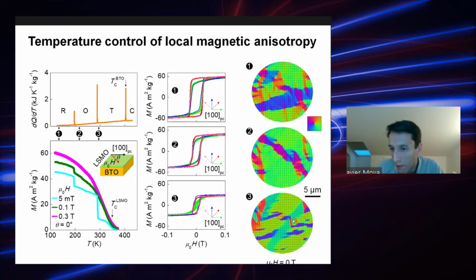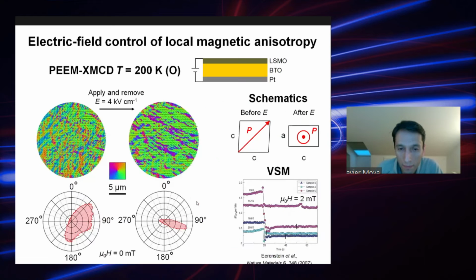We've done magnetic imaging, so you can see that you change the microstructure and you change the local magnetic anisotropy. You can also change the type of anisotropy that you have. So in the tetragonal phase, the material is primarily uniaxial overall, when you take it as a whole. And in the other two phases it is primarily biaxial. So if we concentrate on this uniaxial phase, which is interesting for magnetoelectrics, what we can do is basically do the same experiment that I showed you before, but in this case applying an electric field.